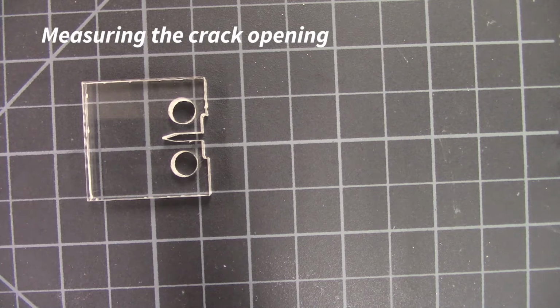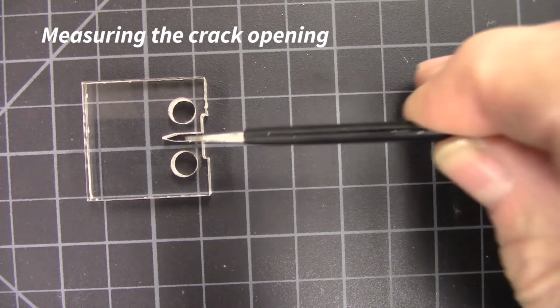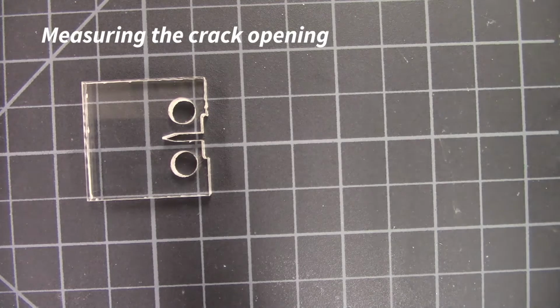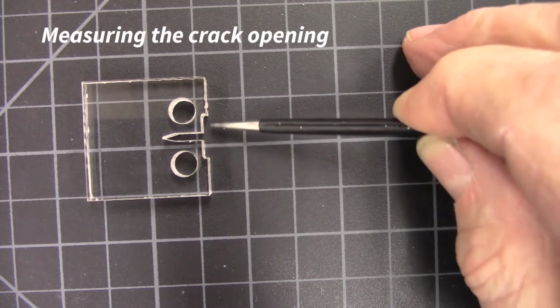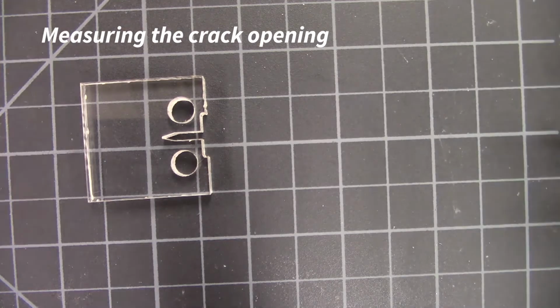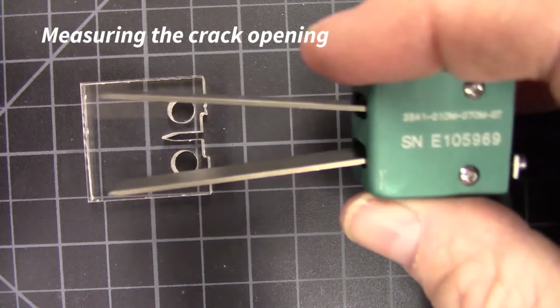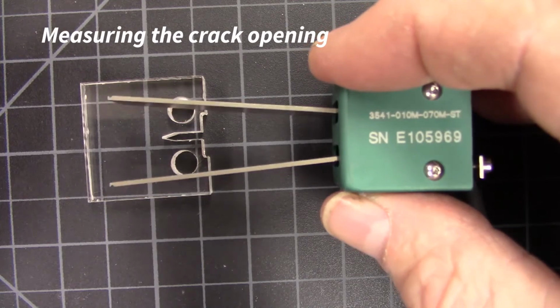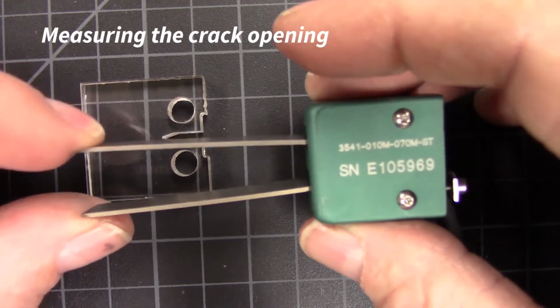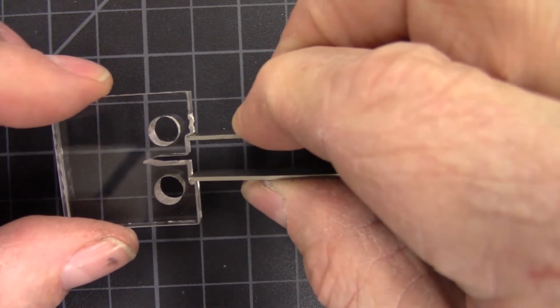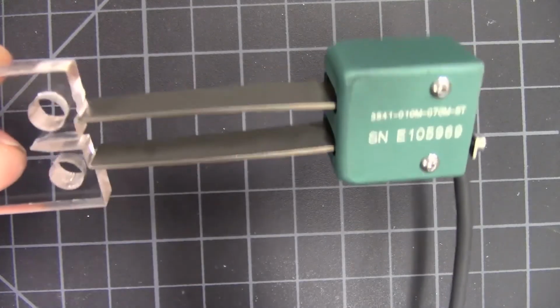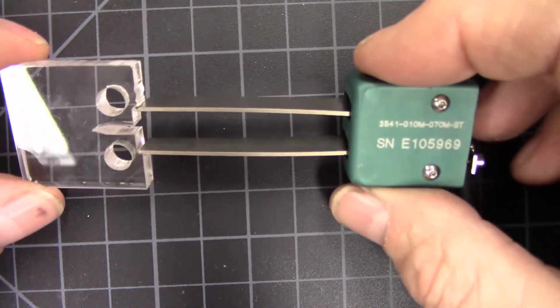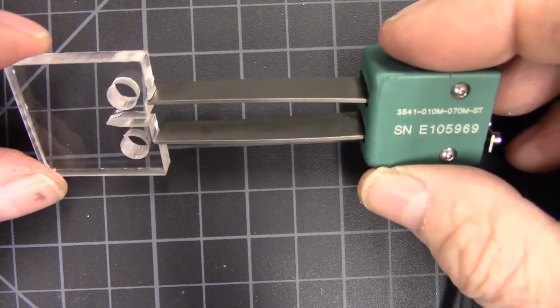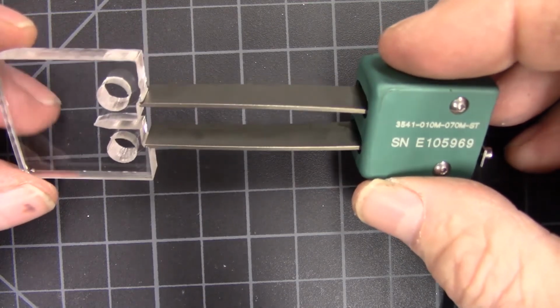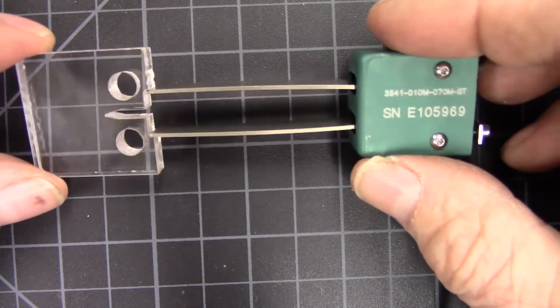So one of the things we need to measure during this test is the crack opening and how it changes. So in order to do that, we've added these features to our specimens, a little pocket with these knife edges. That will allow us to mount this clip gauge, which is similar to the extensometers we used in the tensile tests. There's 2 cantilever arms here. If I squeeze those together and clip it on, it'll just stay there using spring force. So once we start the test, the clip gauge will move with the specimen and we'll get a readout in our data acquisition system in millimeters.